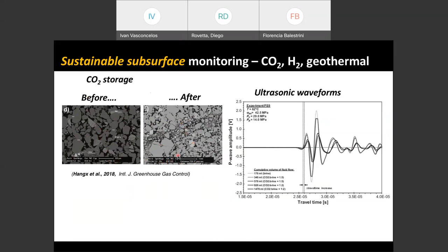What's interesting here is that we actually have some wave data from ultrasonics. So these are standard transducer ultrasonics, but you see the waveforms here. In Susanna's paper, they look at the change in travel time and they try to measure that by looking at the peaks here of the first arrivals. Okay, so they're using that as a proxy for a change in travel time. You can see that the change of travel time is relatively small, but I like to point out at this point that the change in the waveforms is actually pretty significant. You can see it with your eyes with no effort, that the change in waveform starting from the brine sample here towards the black samples clearly shows an increase in attenuation.